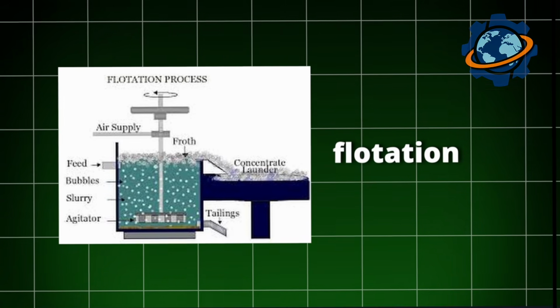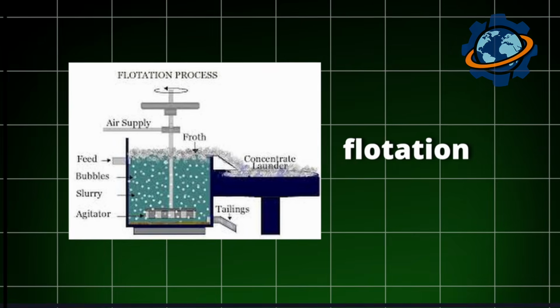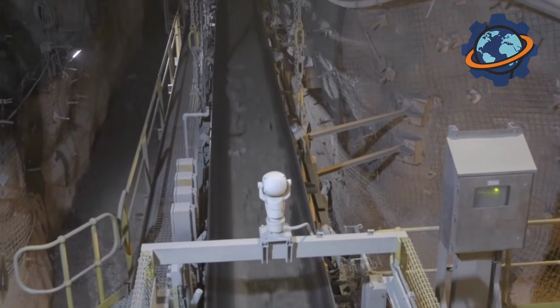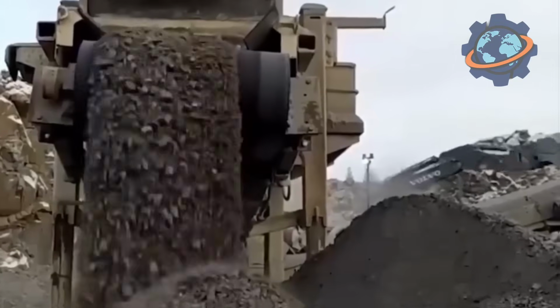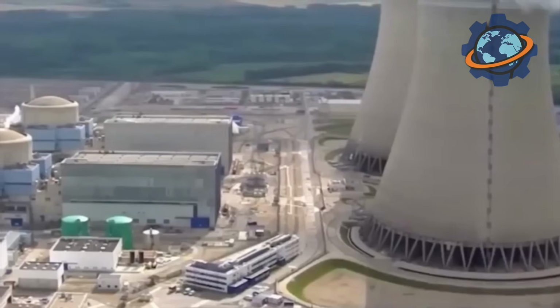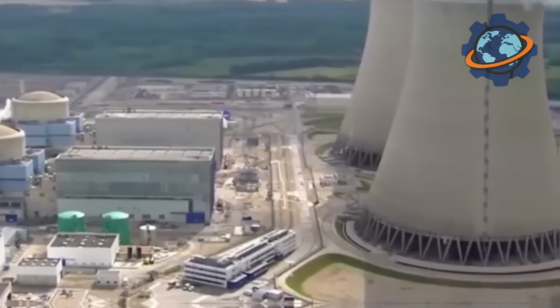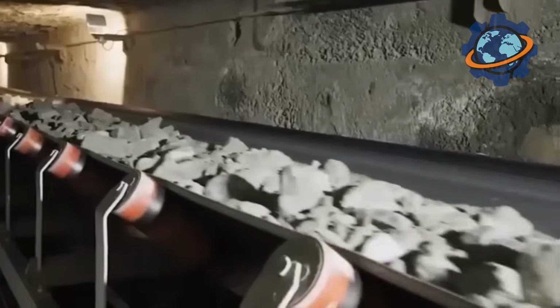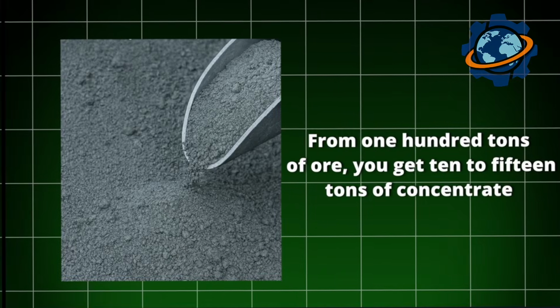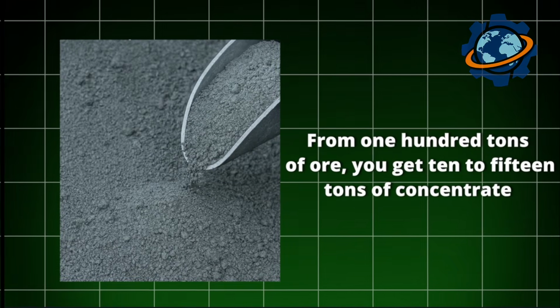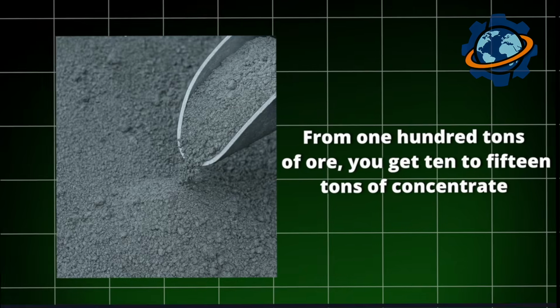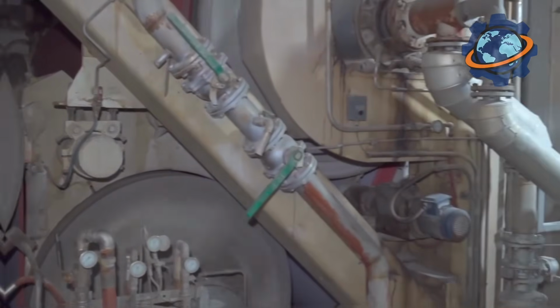Millions of air bubbles rise through the pulp. Particles of sphalerite, zinc ore, stick to the bubbles and float up. A gray foam forms on the surface, 20 inches thick. This foam contains zinc. Waste rock settles to the bottom and is drained off. The foam is collected, filtered, dried. The result is concentrate, powder containing 50 to 60% zinc. From 100 tons of ore, you get 10 to 15 tons of concentrate. This concentrate is loaded into rail cars and shipped to the smelting plant.